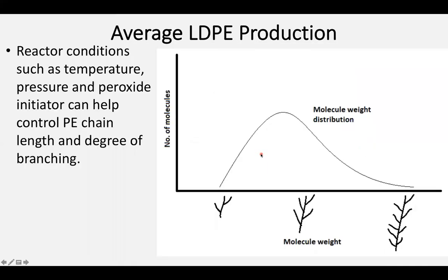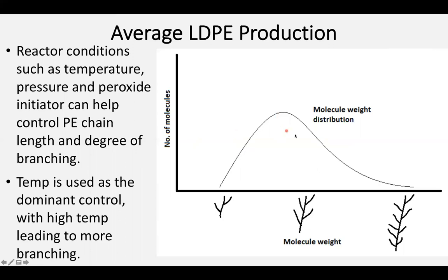One of the other things worth noting is that you can use the reactor conditions to help modify the exact nature of the low density polyethylene you're generating. By changing the temperature, pressure, and peroxide amount, you can change the chain length as well as the degree of branching. Our dominant control is going to tend to be temperature. The higher the temperature of the system, the more you'll move toward lower molecular weights and higher branching. Less initiator is going to give you higher molecular weights and less branching. So you can have fine control over the final product.